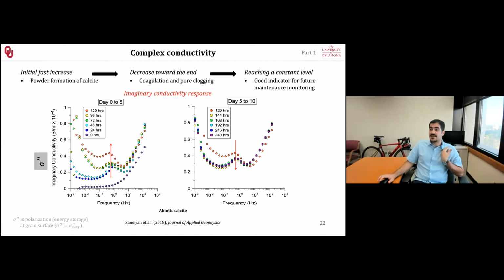But what we were interested in was the complex conductivity method, or the geoelectrical response. In that, we were able to see a peak forming in our imaginary conductivity spectra. You remember the phases I showed you, that we were looking for a peak, right? We didn't have any peaks initially, but as the precipitation continued, we saw a peak forming at around 1 hertz and keeping going up in magnitude until the middle of the experiment, and then it basically starts to go down and reaches a constant level.